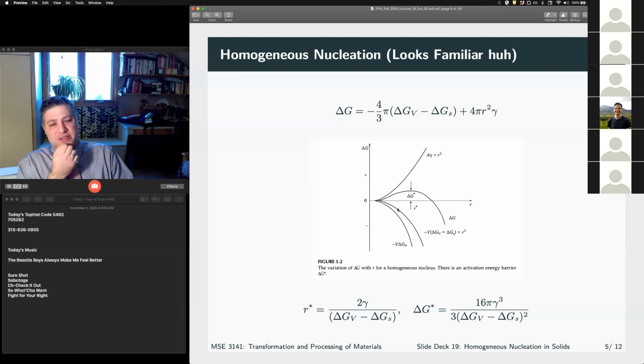So this curve is really what we want, is our delta GV minus delta GS, our volume term minus our strain term. And that pushes this line out here. So that means we're not getting as negative as quickly, right? So that means our surface energy term dominates for longer, right? And when that happens, our activation energy hump increases, and our R star gets pulled to longer and longer lengths.